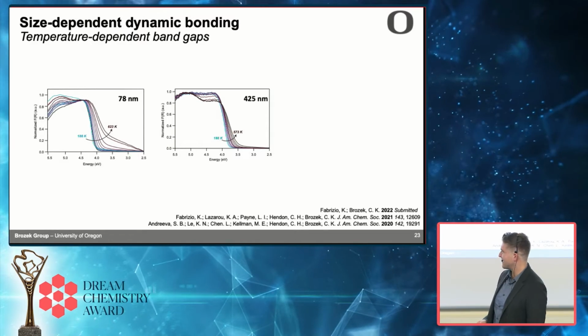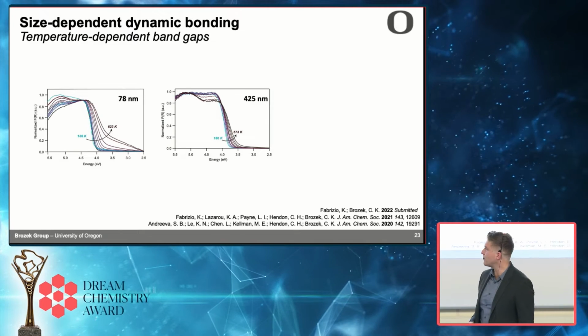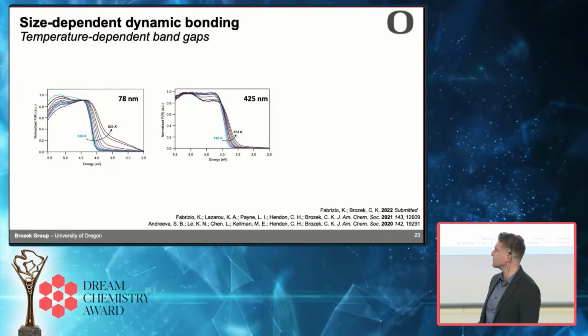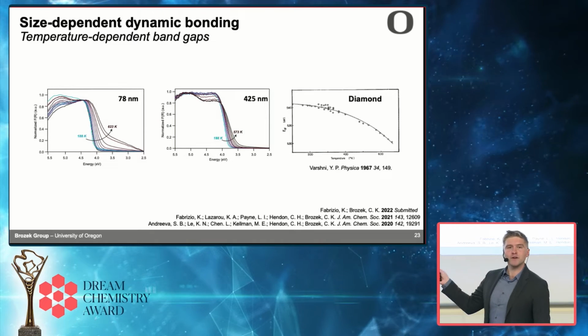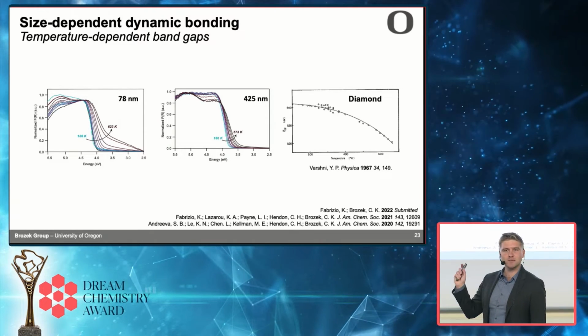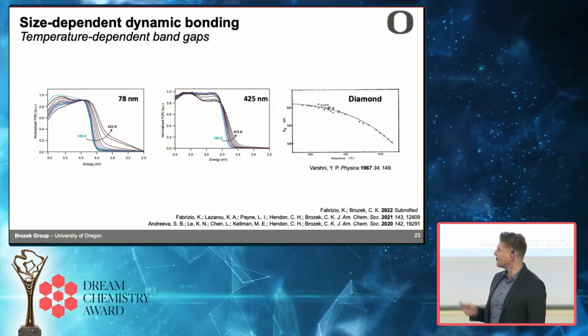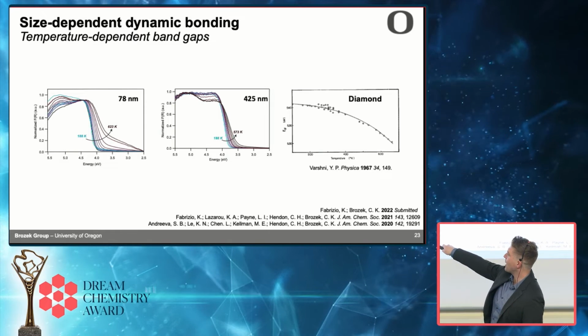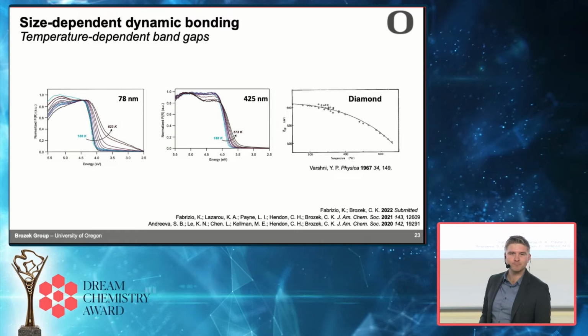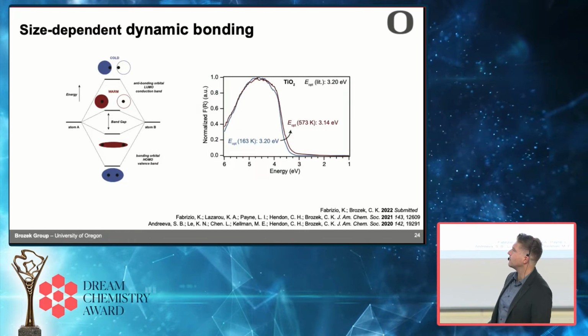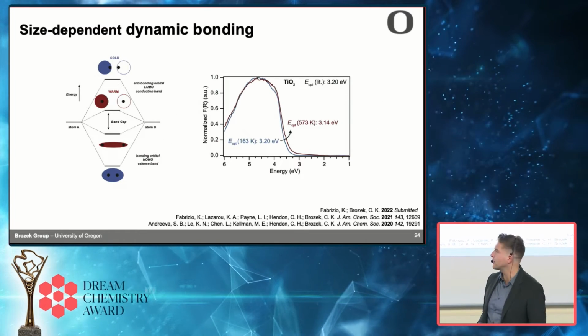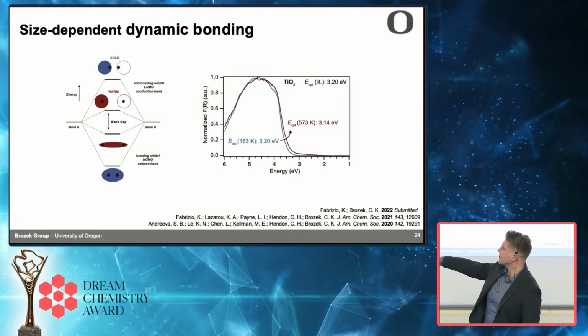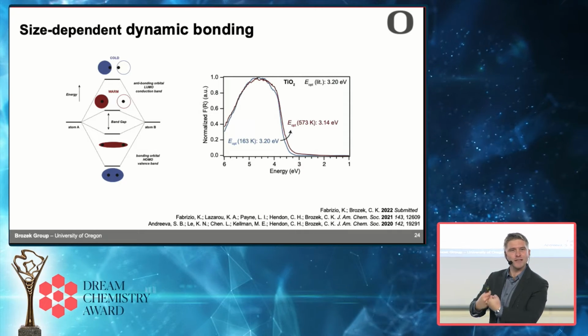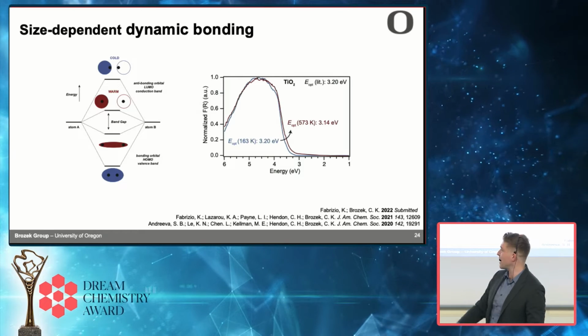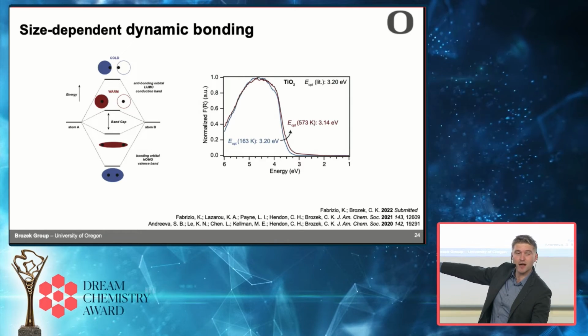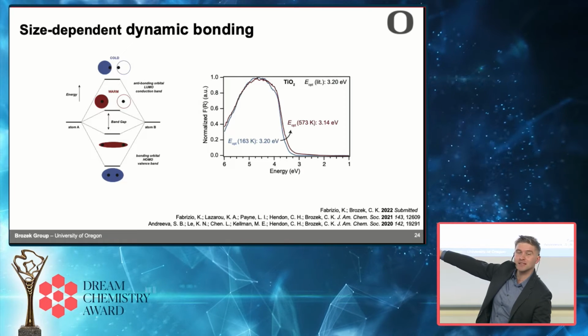And I was scratching my head and thinking, what could be causing this? And I thought back to my postdoc days when we were studying traditional semiconductors, and I remembered that every semiconductor shows behavior like this. Diamond, silicon, germanium, everything will show that the optical gap will redshift as you heat it, okay? And the reason for this you can think of in terms of simple MO theory. At low temperatures, your atoms are sitting close to each other, they're making really nice strong bonds, there's really good orbital overlap, and so your bonding orbital is really stabilized, and your anti-bonding orbital is really destabilized.